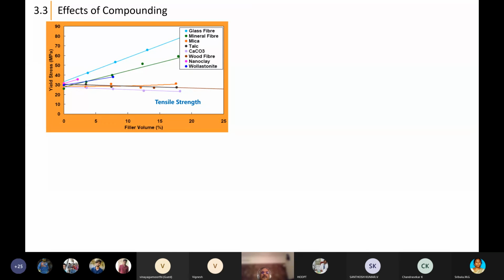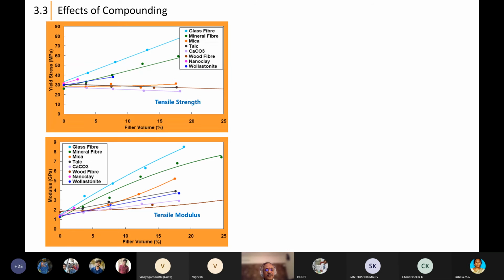This is another graph that tells you different types of filler and what is the effect on the polymer for different properties. Okay, this is tensile strength. You can see the blue one talks about the glass fiber. Glass fiber, as the filler volume goes up, has got the maximum increase. The green one shows mineral, it is lesser. Then you have mica, calcium carbonate, wood fiber, wollastonite, nanoclay, all these things are there. So a very distinct property increase can be seen in glass fiber followed by mineral. This is for the tensile modulus. Same grade, same thing done on nylon.